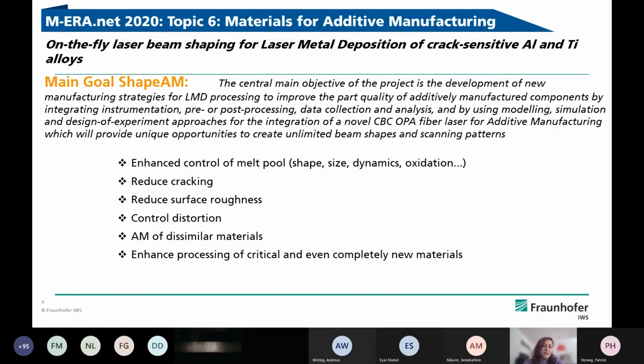The sub-goals, as we have been hearing in the different presentations today, are using this innovative laser beam shaping to enhance the control of the melt pool for additive manufacturing. It means to enhance the control of shape, size, dynamics, and oxidation issues related to the melt pool. Reduce cracking, which is an issue not only for aluminum and titanium alloys, but also for high temperature alloys like nickel-based superalloys, which we will be focusing on later. Reduce the surface roughness by tuning the laser intensity, which is feasible with the beam shaping.